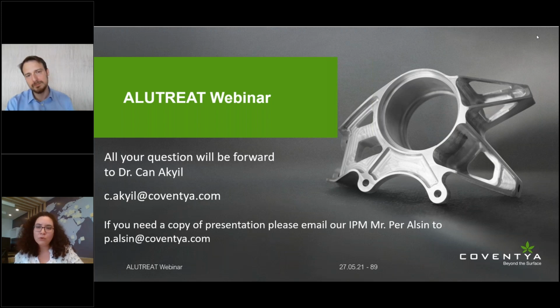There is a lot of questions about the extrusion quality and alloying element relation with coloring. Is there any relation between the extrusion quality and coloring? Of course. When you do the color, the first thing you realize is that if you're doing the coloring on a mill finish sample, wherever those streak marks are, they will appear either darker or they will have a brighter color. And it's exactly the sample that we have shown, which was unevenly etched. So again, the same goes for the alloying elements.